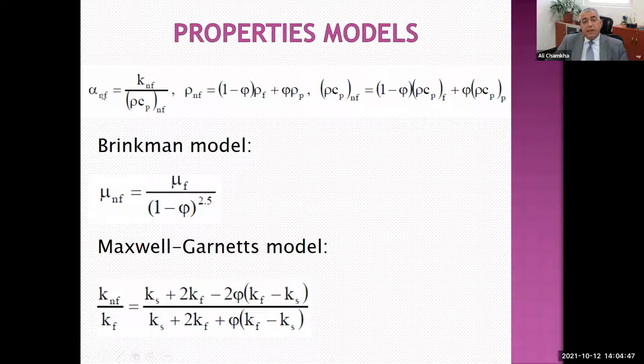Here you will see the thermal diffusivity definition, the density, and the specific heat at constant pressure for the nanofluid, and how we calculate them. Phi is the volume fraction. For example, for the dynamic viscosity of the nanofluid, in the early stages we use the Brinkman model. This involves the viscosity of the base fluid and the volume fraction.